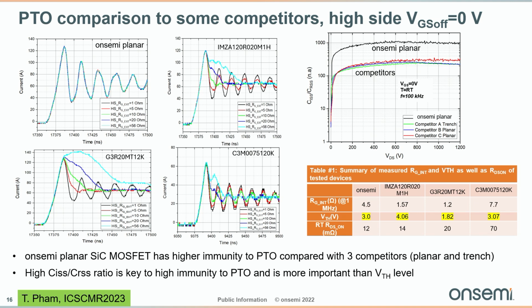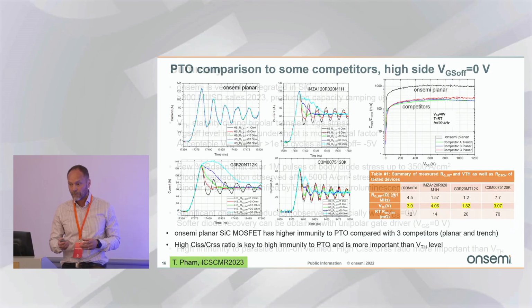Other devices are still pretty good, I would say. But what we want to highlight here with this one is that the ratio of CISS to CRSS is the key thing for high immunity to parasitic turn on. And it's more important than the threshold voltage level, as you can see that one of the devices has a higher threshold of 4 volt, which many customers like to avoid parasitic turn on, but it's not the key thing. It's the ratio of the CISS to CRSS. So high VTH can be operated with.